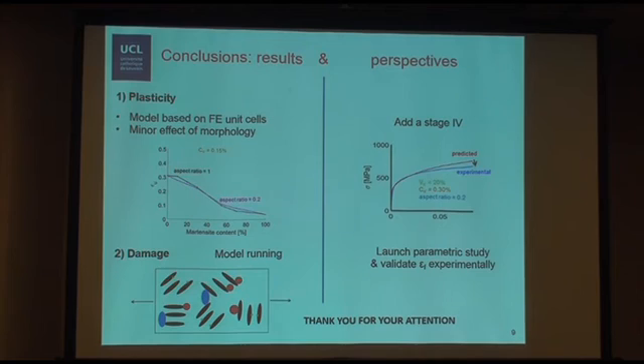Alright, to conclude, I am working on dual phase steels with a plate-like microstructure, because we have seen that we can really boost the fracture toughness by modifying the shape of the martensite inclusions, here platelets. I modeled the plasticity of the steels using finite element calculations, and the big conclusion was that morphology only has a minor impact on the elastoplastic behavior. The model works quite well already, but for an even better match, we are adding a stage 4. And we also worked on the development of the cellular automata approach for damage.